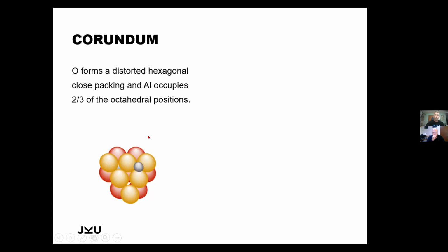Here we have 1 on top of the position where 1 aluminum is in the layer below, and the next one is on a position where in the layer below is no aluminum. So we do not always fill the same voids with the aluminums, but they are rotating more or less. So every 2 out of 3 voids are filled with this aluminum.